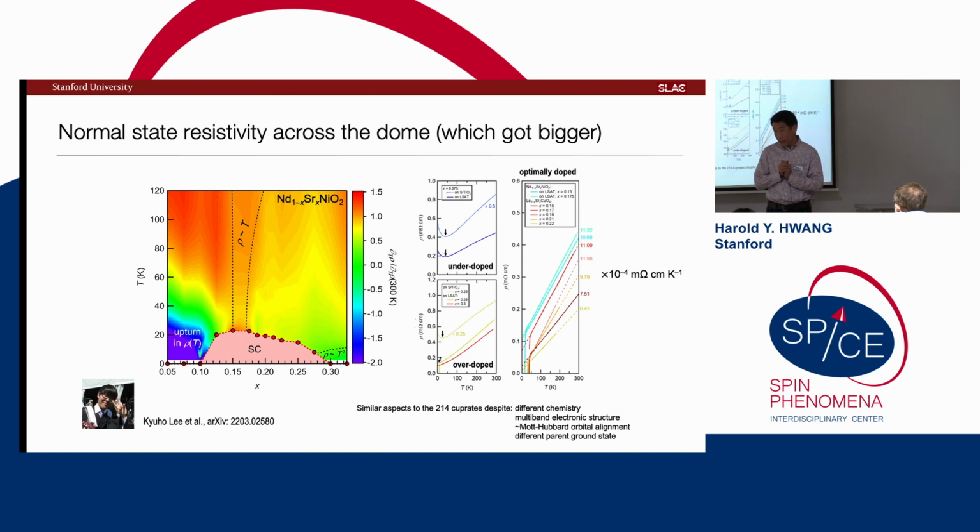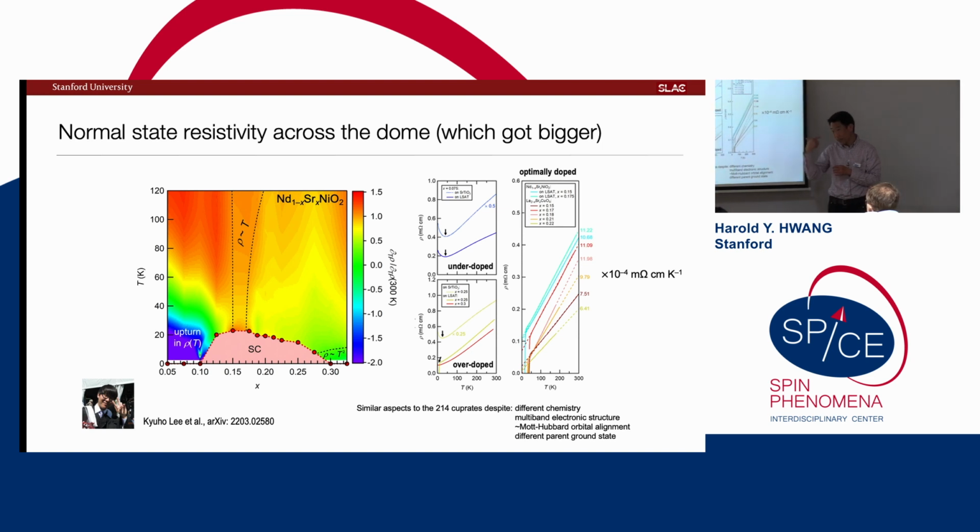Stimulating. So let me see. Their proposal is the following. Their nominal electron count is 7.5 d electrons. They've got a bilayer. So theirs is actually closer to these quantum well ideas, right? Where you basically have bonding and antibonding combinations, and you do this sort of thing to get where you want to be. So very interesting. It would be another way to get a spin-1/2 system in the x squared minus y squared channel. I'm getting recorded, so I have all sorts of speculations. I don't know how to interpret the other business, but it's certainly very suggestive.